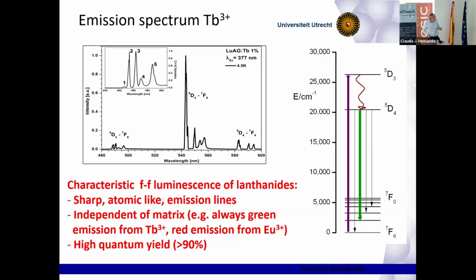There we see the emission spectrum. And you see some sharp lines around 490 nanometers. That's due to the transition from 5d4 all the way back to 7f6. Around 550 nanometers, you see some sharp lines due to 5d4 to 7f5. Around 590, 5d4 to 7f4. And what is special about this is that it's very sharp emission lines. And that is unusual. Normally, if you have ions in the solid state or ions in solution or organic molecules, you get broad emission bands. And the reason is there's a strong coupling with vibrations. So we have combined electronic and vibrational transitions, vibronic bands. You get broad bands, not for the lanthanides.